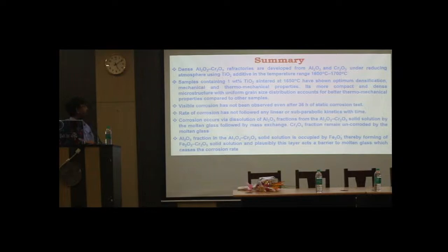Okay. So dense alumina chrome, we developed in the temperature range 1600 to 1700 degrees centigrade. And since 1% titanium gives better thermomechanical strength, with uniform grain structure, that's why we selected this sample for the corrosion study. And in all the samples, there is no visible corrosion, even after 36 hours. But the rate of corrosion does not follow any linear or subparabolic kinetics with time.